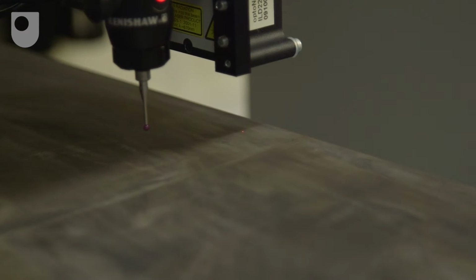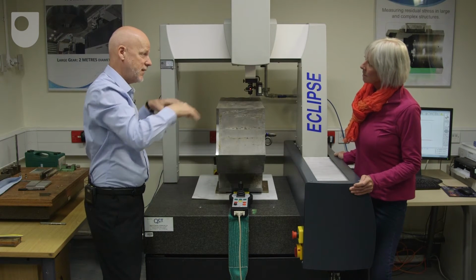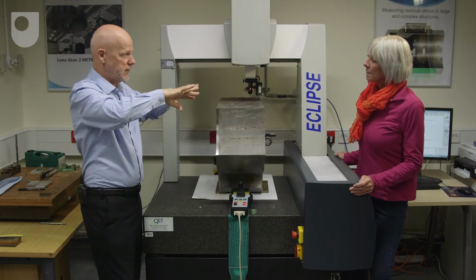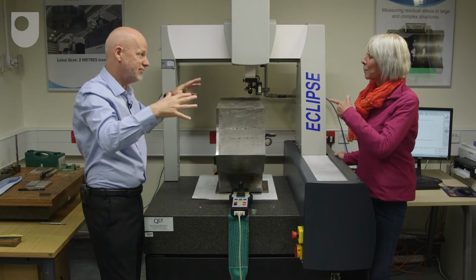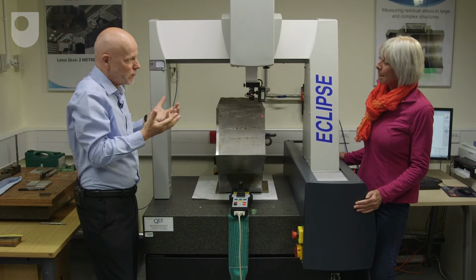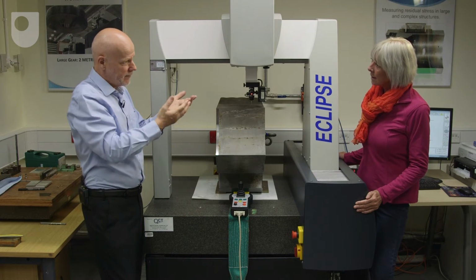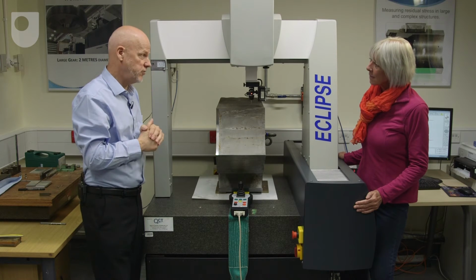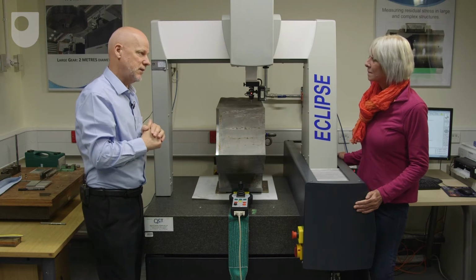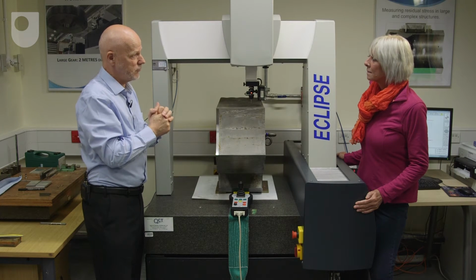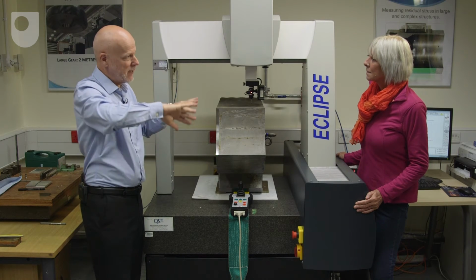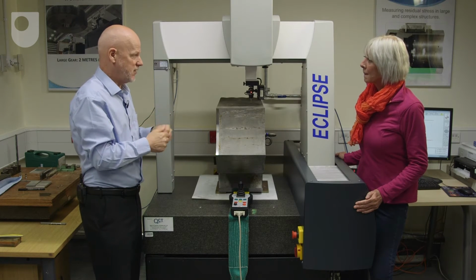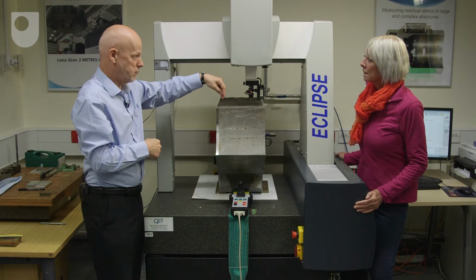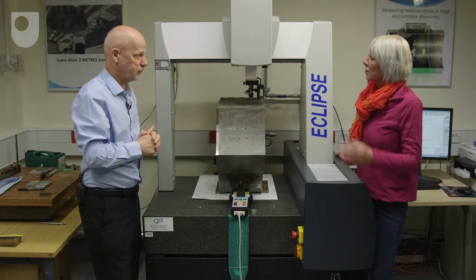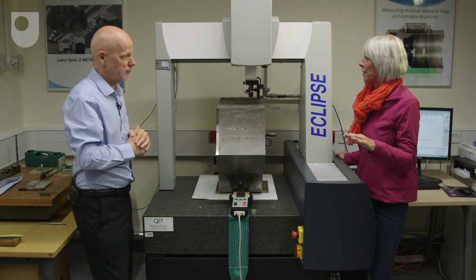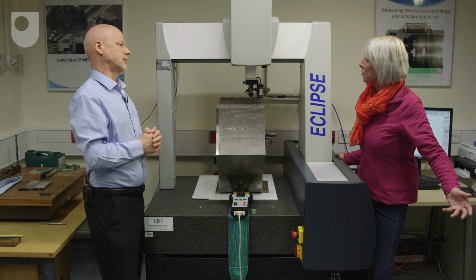So we'll get a cloud of data associated with this cut surface, which will define the contour. Oh, like a contour map of the surface? Exactly. Yes. So that's a deformed surface. And then we apply that deformation to a virtual computer model and carry out a stress analysis from which we can infer a map. A stress map? Of the stresses, yes, which are acting normal, perpendicular to this cut face. Right. So that will show any residual stress which can then be manufactured out in future components?